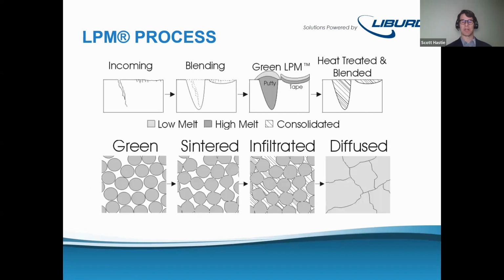And then at a certain temperature, the low melt alloy is going to infiltrate into the interstices between the high melt alloy balls, and then it's going to be held there for a period of time where you also start to see diffusion of constituents from the braze into the base alloy, high melt alloy, and then in the other direction. And then eventually you get a diffused super alloy material. Our last step is to heat treat and blend that surface back to shape, blend or machine or even form, as we'll see very shortly.